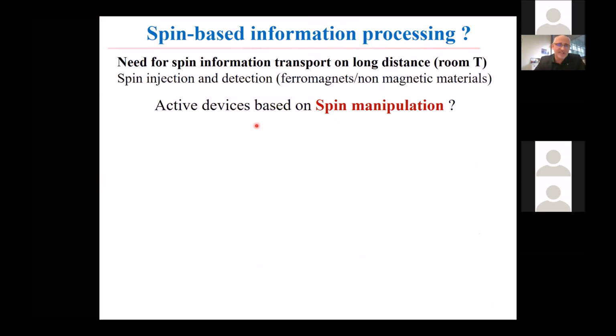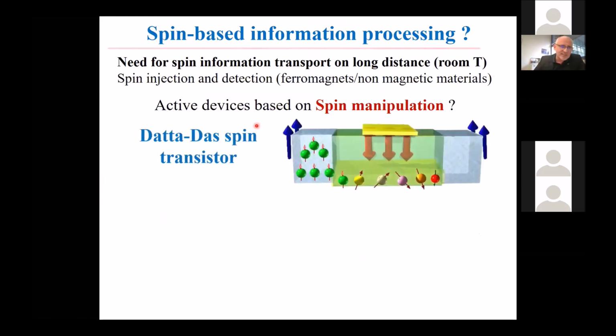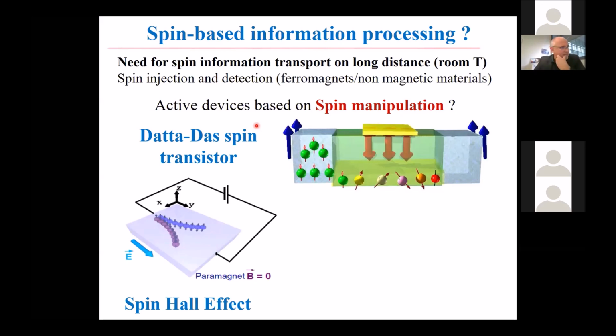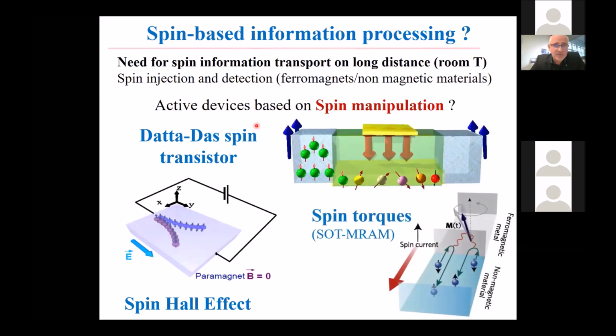We want active devices. And as you know, the Datta-Das spin transistor using an electric field was the first proposal, which has been difficult to implement. There have been more recent proposals and discoveries with the spin Hall effect, where in the absence of a magnetic field, just because of the strength of spin orbit coupling, you can actually create pure spin current. And eventually this spin current can be used in spin torque phenomena, so that you can transfer angular momentum to magnetic materials, so that you can make the magnetization precess or reverse. So this kind of spin manipulation is very interesting.